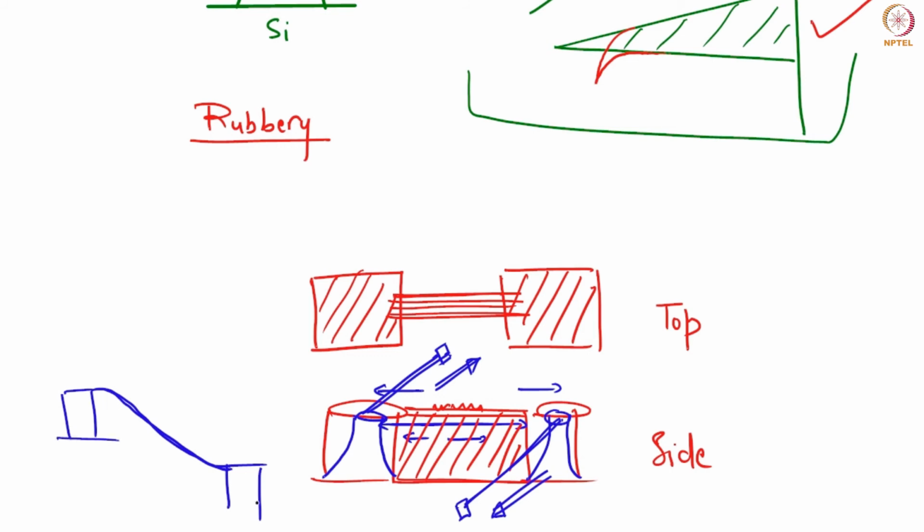So basically, these are the kind of structures you can make. The idea is to make non-uniform stresses or structures which will, after shrinking, undergo non-uniform stresses, and then you can accordingly study the deformation behavior. If you do see deformation but a continuous structure, so this is your polymer, let's say your wall became like this, but it did not break, or your fiber got pulled but did not break, it just became thinner. In that case, this is your necking process.